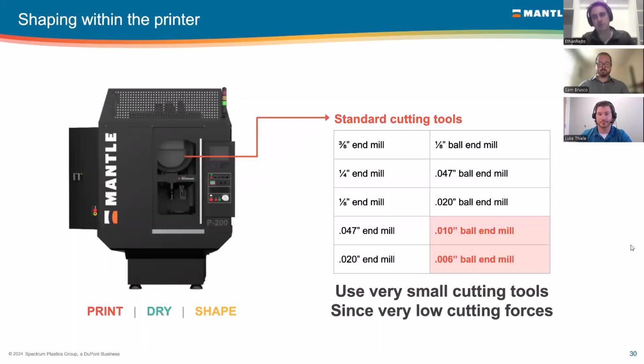One thing I wanted to reiterate is that one of the coolest and most beneficial parts of our process is the ability to do this shaping and refinement when the part is in a very soft state. We're using standard cutting tools inside of our machine. There are 10 of those tools we're using today. But since we're only machining layer by layer, and essentially a paste material, there are very, very low cutting forces on the tools, which allows us to use some very, very small cutting tools.